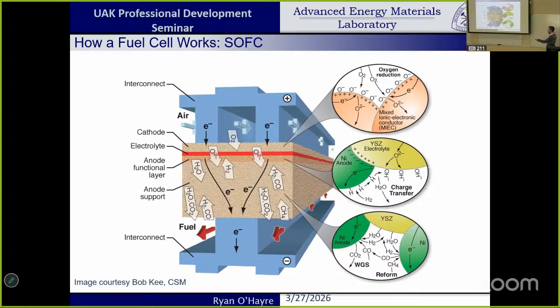So now this is the heart of the fuel cell. We call this the membrane electrode assembly. The electrolyte is this dense red layer. That's a dense, thin ceramic on the order of 10 microns. The cathode electrode is also pretty thin, typically 30 microns. So these 2 layers combined are like 40 microns. You can barely see it with the naked eye.